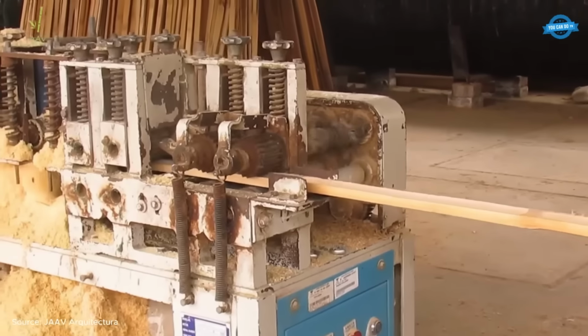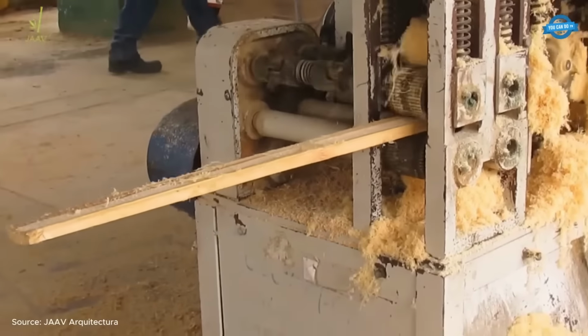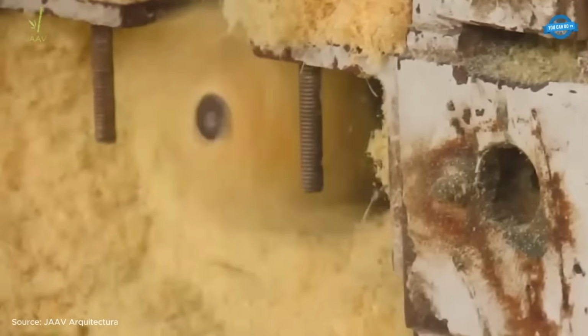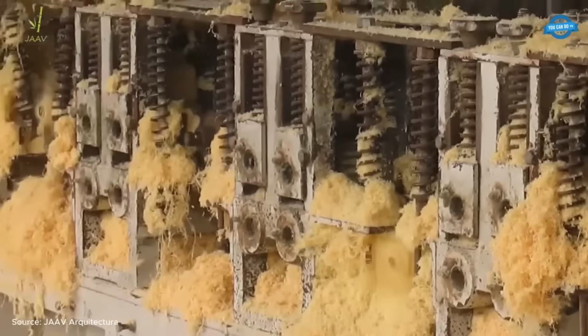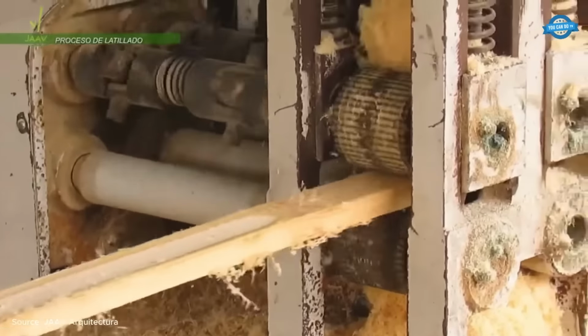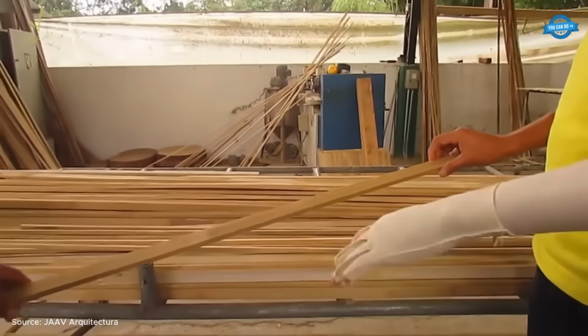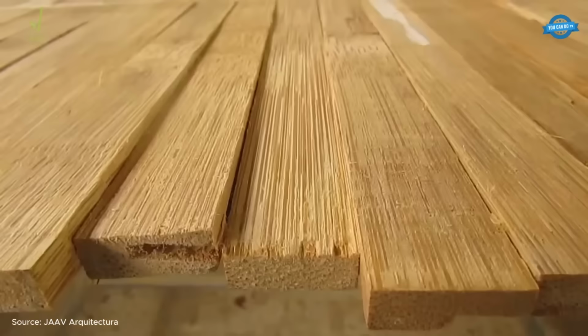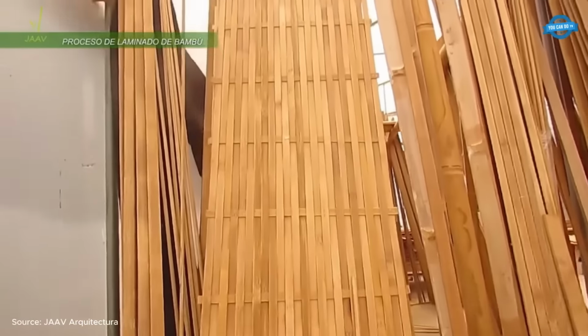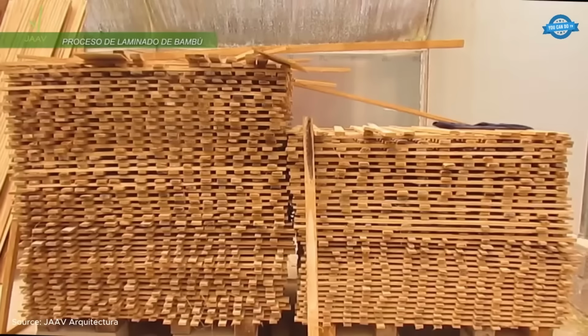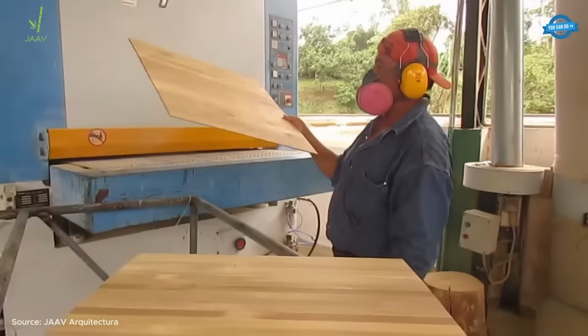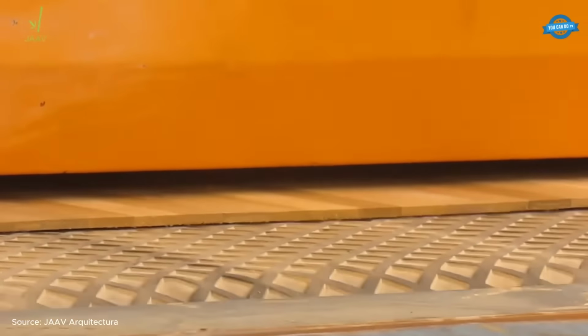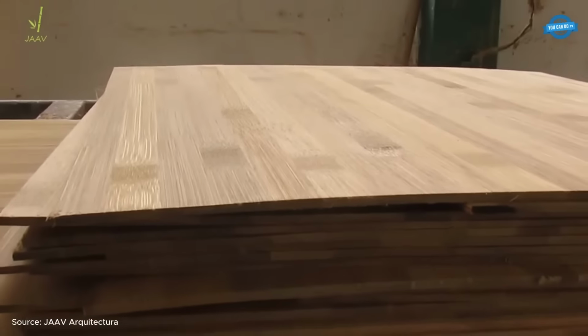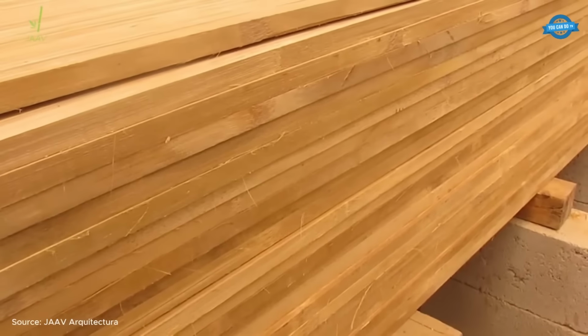After drying under controlled conditions, adhesive is evenly applied to the bamboo surfaces. The strips are then aligned and layered according to the required grain orientation. High-pressure hot pressing bonds the layers into solid laminated boards. Finally, the panels are trimmed, sanded, and inspected, producing durable bamboo laminates ready for flooring, furniture, or architectural applications.